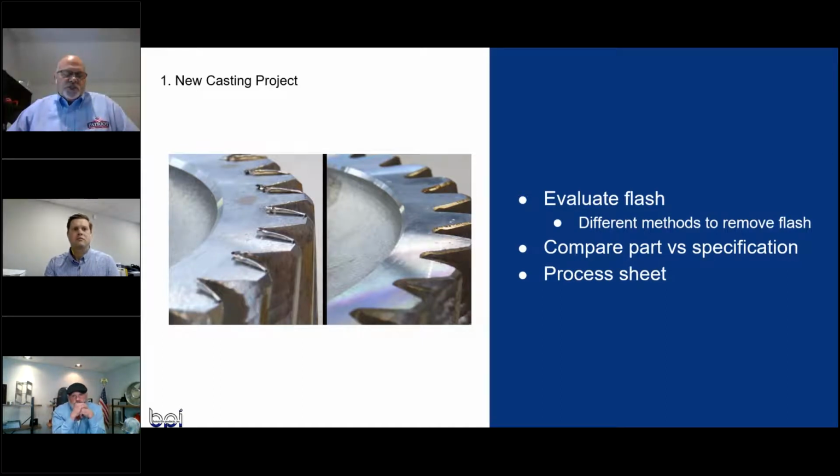Tim, that's a great question. The good thing is the steel parts, absolutely, you can batch those with the casting when the castings are prepared for finishing. Normally, aluminum extrusions can stand the heat as is, the way that they're made. So if it is an assembled part that you're going to be liquid coating or powder coating and it is a baking system, your secret is your cleaning. You would want to use a multi-metal coater cleaner, because for paint to adhere to aluminum, you have to have fluoride in your cleaner. Now, it's a very small percentage of fluoride, but without the fluoride, especially on extrusions, the paint will not adhere. You will have loss of adhesion.